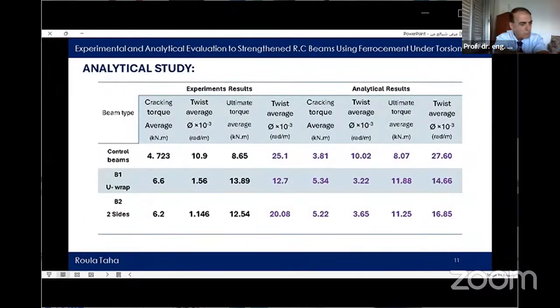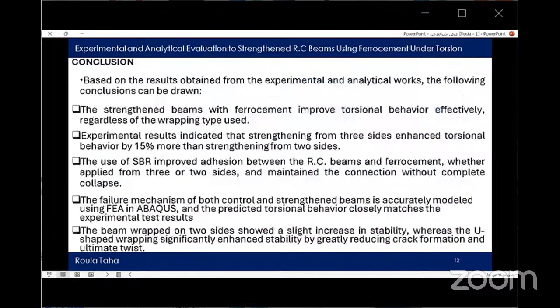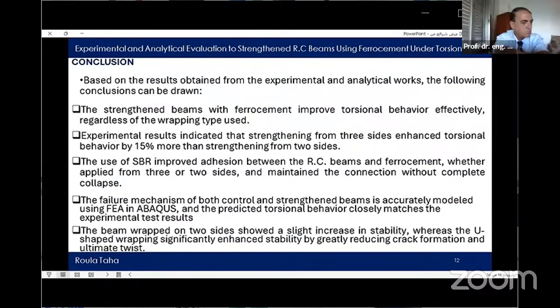The results of the analytical and experimental tests are presented in this table, where we can see the matching results. From the above, the following conclusions are drawn. Strengthening beams with ferrocement satisfactorily improves the torsion behavior regardless of the wrapping type. Experimental results showed that strengthening from 3 sides enhanced torsional behavior by 15% more than strengthening from 2 sides. The utilization of SBR enhanced adhesion between the RC beams and ferrocement, whether applied from 3 sides or 2 sides, and maintained the connection without complete collapse.